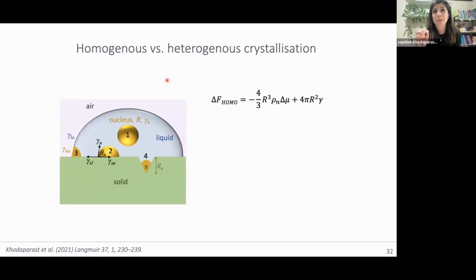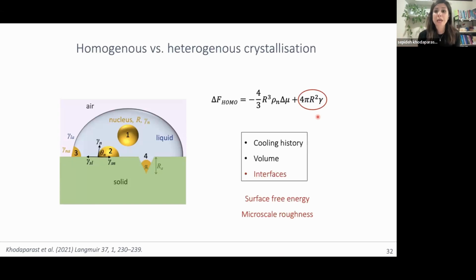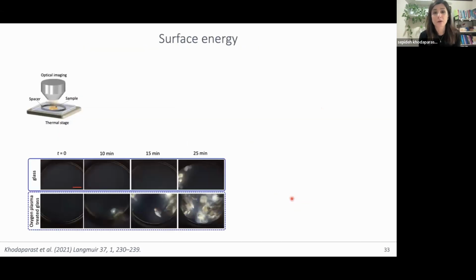Besides the resolution, the waiting time, and the volume of the sample, we concluded already that we don't have homogeneous nucleation, and all of our nucleation is actually happening on the surface. When you have nucleation on the surface, there is the effect of heterogeneous nucleation. You have the effect of the surface energy and surface roughness. So when you think about the interface between the liquid and the surface, there are at least two different things you should be looking at: the surface free energy and the roughness.